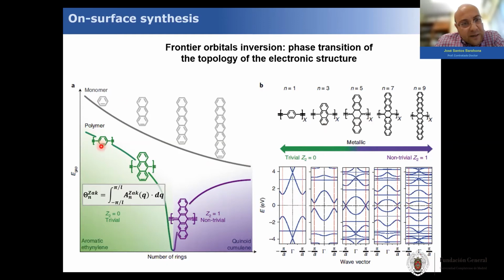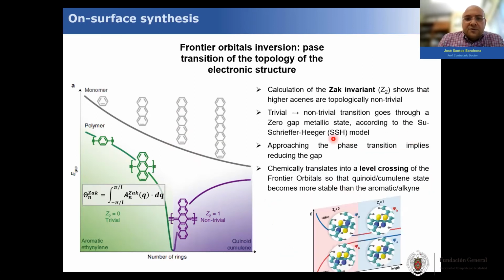As you can see here, when we calculate for the phenylene polymer and anthracene polymer, they are trivial, which is the normal electronic structure we are used to. And in the case of the pentacene and bisanthene, we are in the non-trivial range. So what does this actually mean? These two phases are separated by a phase transition. So in this boundary, as in the Su-Schrieffer-Heeger model, when you go from one phase to the other, we must pass through a zero gap state.